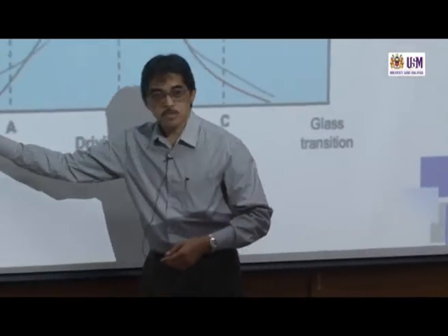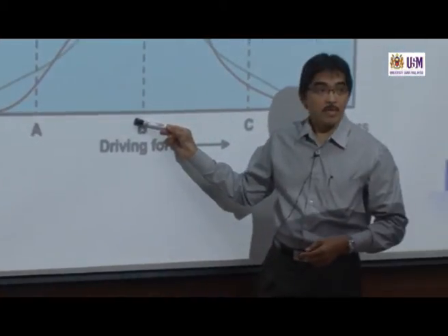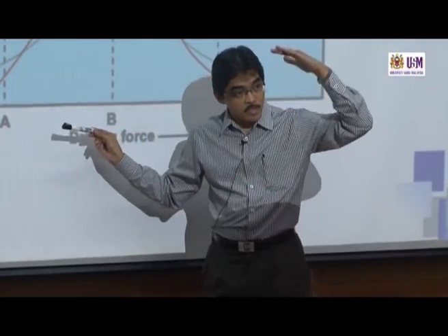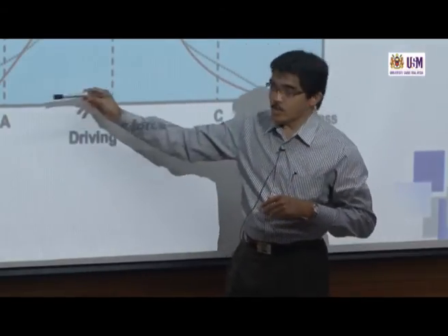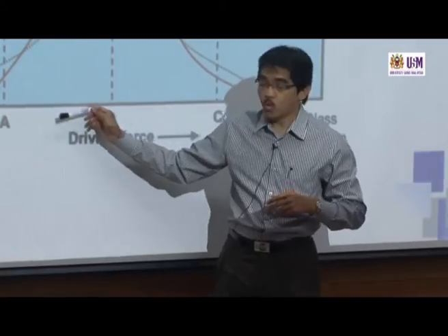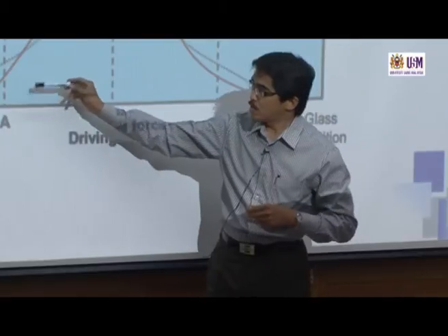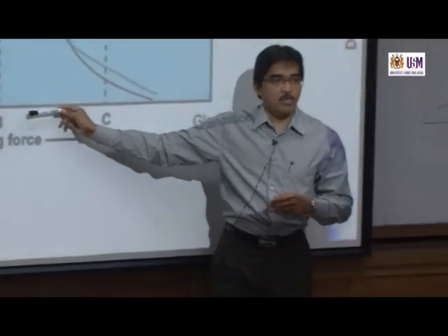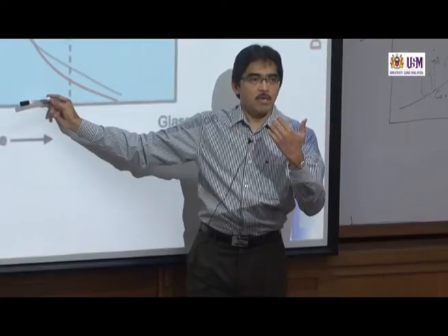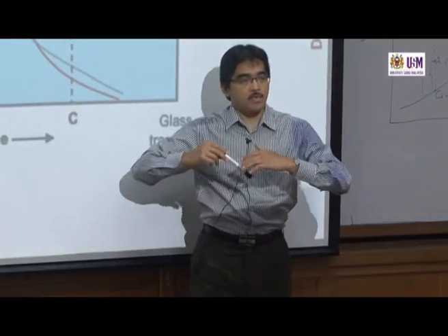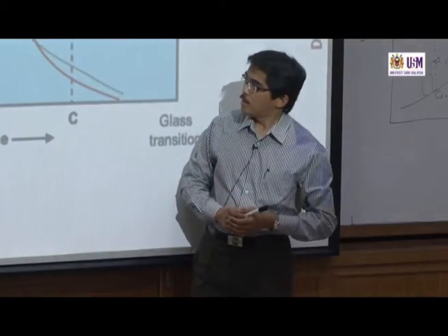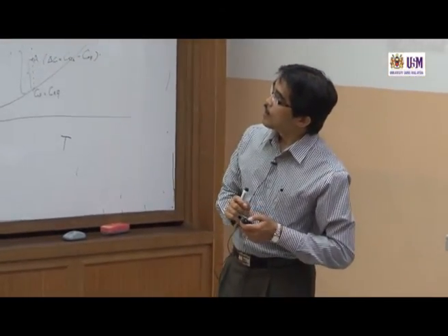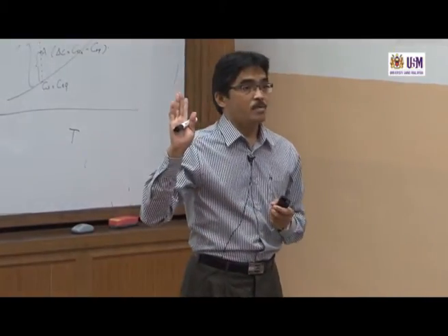Initially, yes, the driving force increased from point A to point B. Why? Because the degree of supersaturation increases. The viscosity is still relatively low, so the molecules can start the nucleation. But from point B to point C, actually, the driving force is now getting lower, because the viscosity increases. So that is nucleation. We are done with nucleation.